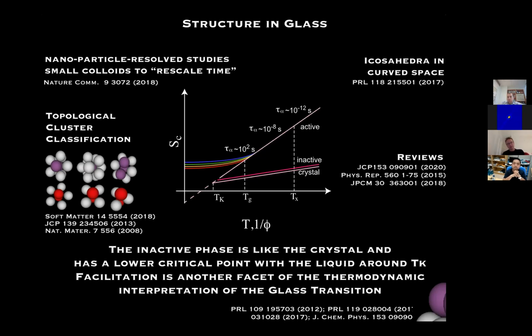But in high dimension, the physics is actually rather different, because the dynamics stop at the mode coupling transition. There's a complete solidification at the mode coupling transition in high dimension. So it's only in lower dimension that one has any meaningful dynamics at temperatures lower than the mode coupling temperature. So then the question is, can one devise a system which is devoid of local structure? Now, we've been looking into this actually, and so far we've failed miserably.